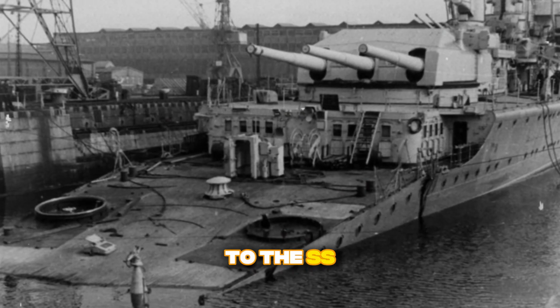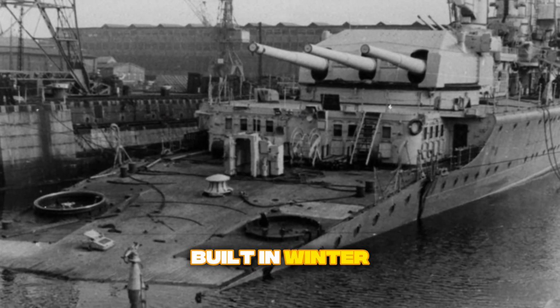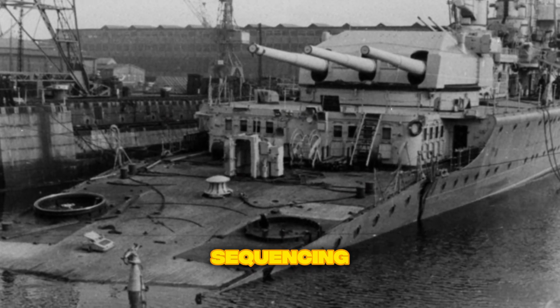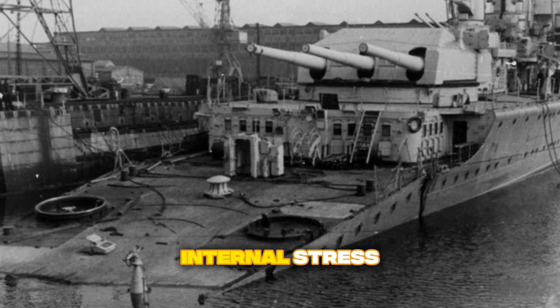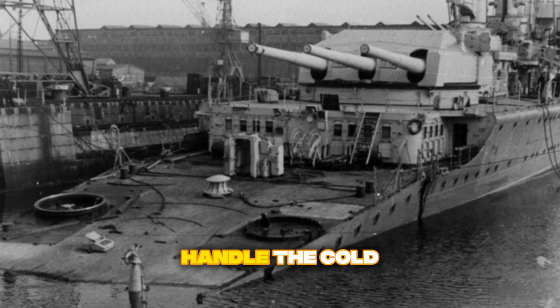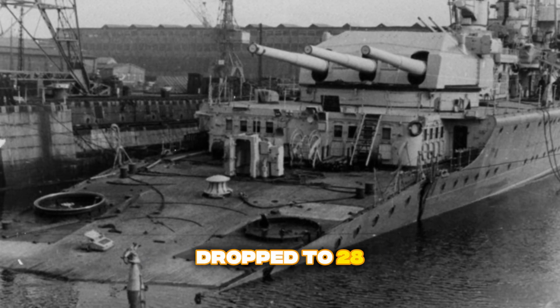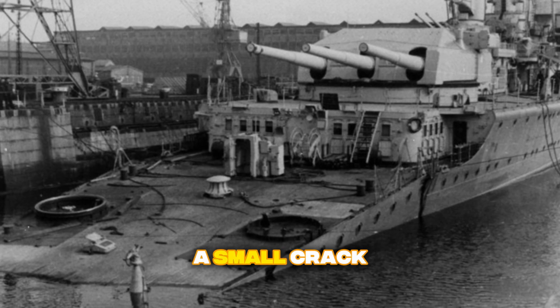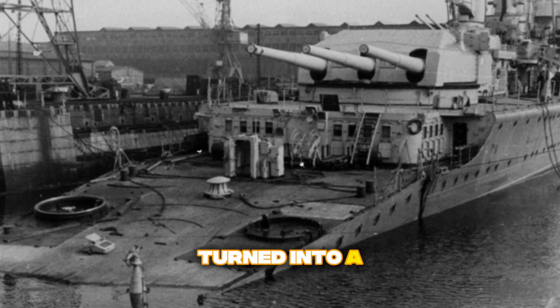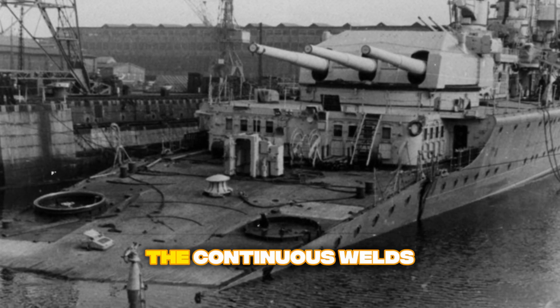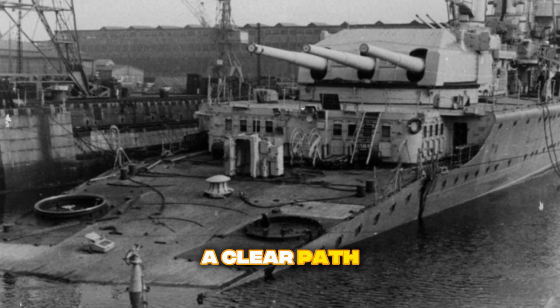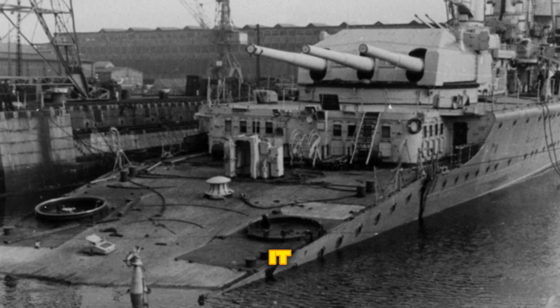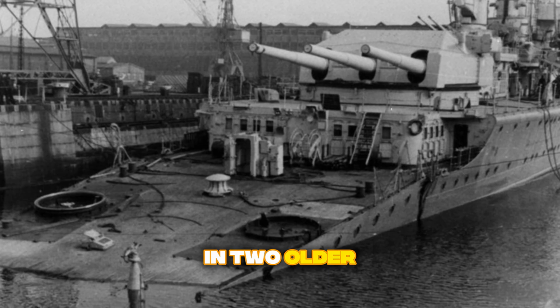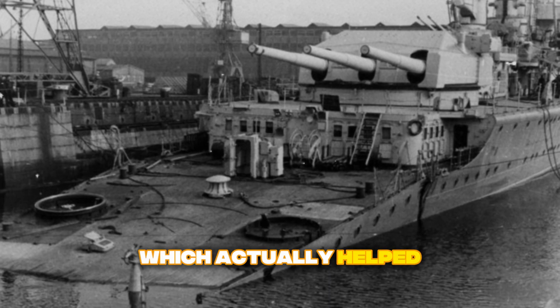That's what happened to the SS Schenectady. Built in winter, welded using poor sequencing and holding millions of pounds of internal stress, her hull couldn't handle the cold. When the temperature dropped to 28 degrees Fahrenheit, a small crack near a hatch corner turned into a full-blown fracture. The continuous welds gave the crack a clear path, and with no rivets to stop it, the ship split in two. Older ships used rivets, which actually helped.